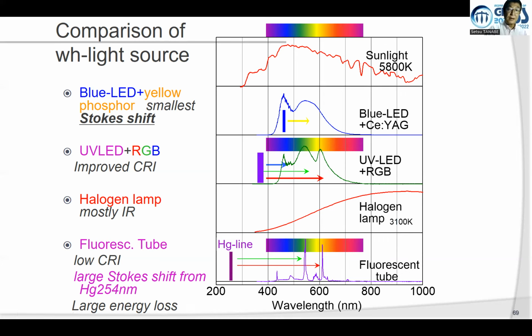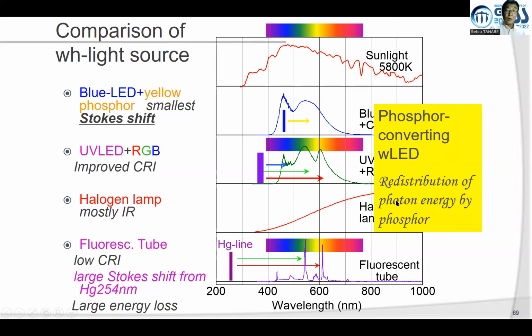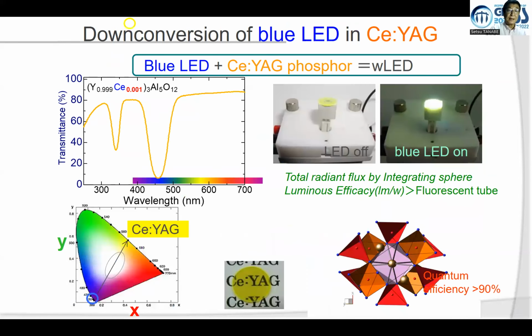And even near UV LED pumped RGB LED can achieve better color rendering index. Also, although less efficient than blue LED-based white LED, compared with fluorescent tube, it is very efficient, and no waste in infrared and a little bit of waste in the UV region, but much better than halogen lamp, you can see. So the role of phosphor in phosphor converting white LED is a redistribution of high photon energy into lower photon energy by phosphor materials, downshifting.